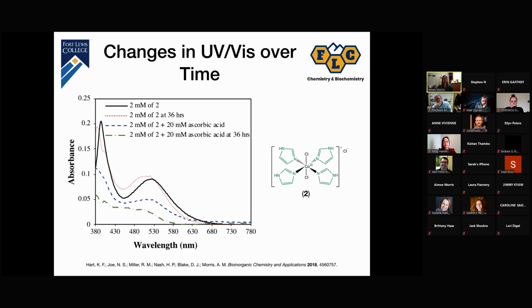And so there have been many studies involving how does that ruthenium compound work? And one of the things that I can definitively say is that it causes a lot less side effects. And there seems to be a mounting degree of evidence that the ruthenium doesn't bind to DNA targets like traditional platinum chemotherapeutics, but it seems like it might be binding to protein targets. Specifically, it looks like amino acids with things like nitrogen and oxygen donors. So there's been some really cool studies in terms of XAS and things like that to probe the oxidation state, as well as things that it can bind to within these complex systems.